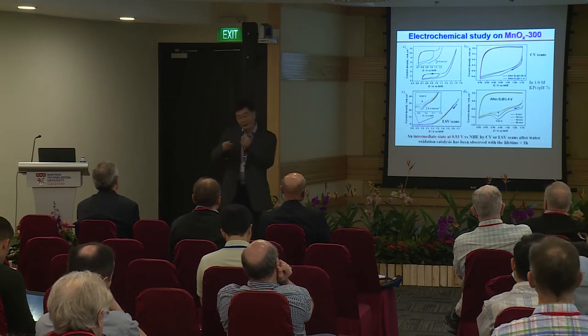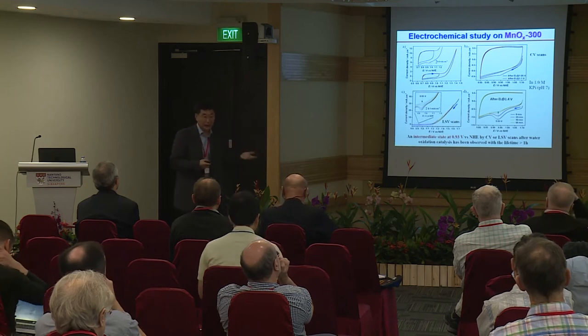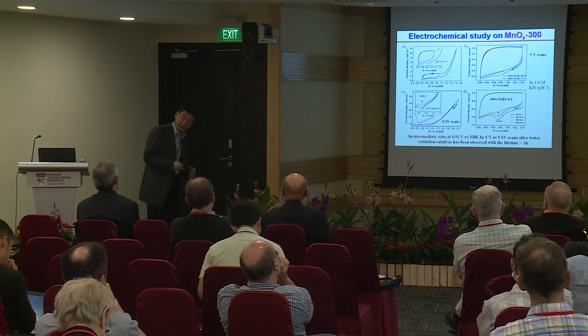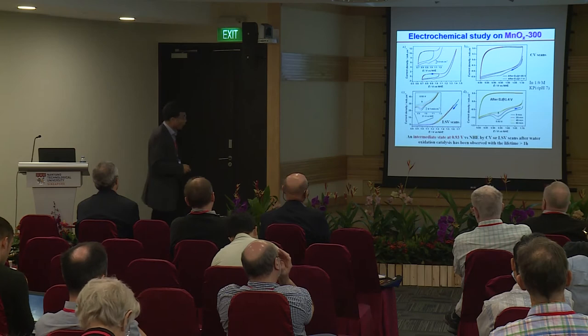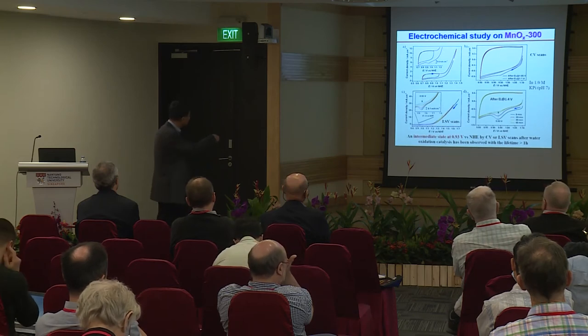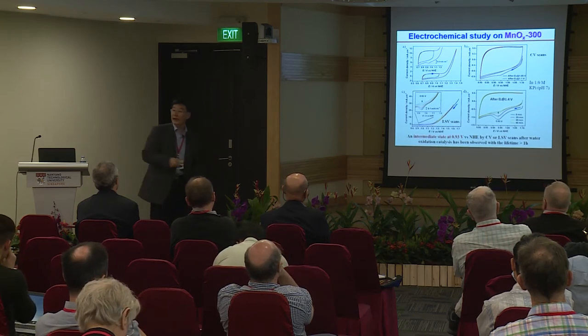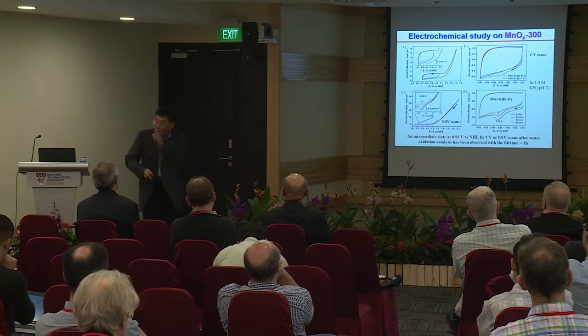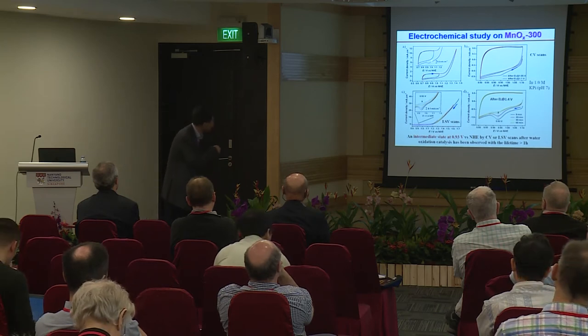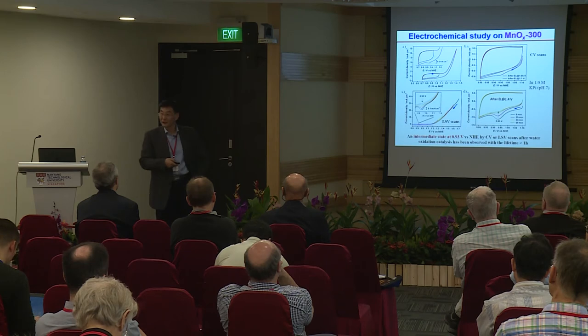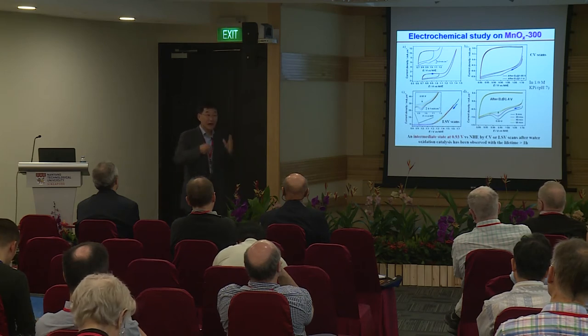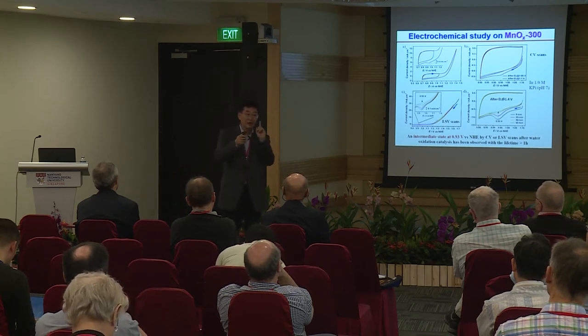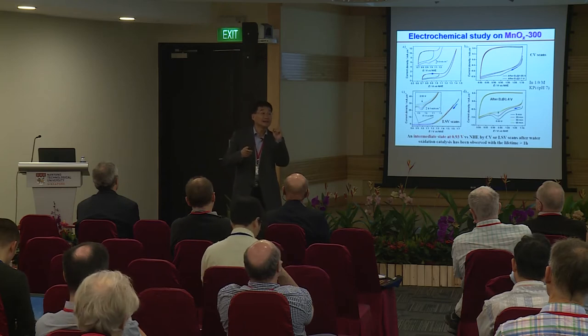So we have made a deeper study by electrochemically driven water oxidation of this manganese oxide. After the catalytic current here, if we make a reductive scan, we found a new wave here. That's to our delight. We are getting very excited. That means after the catalytic cycle, we observed an intermediate state.